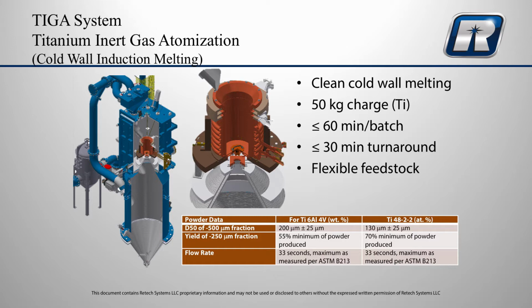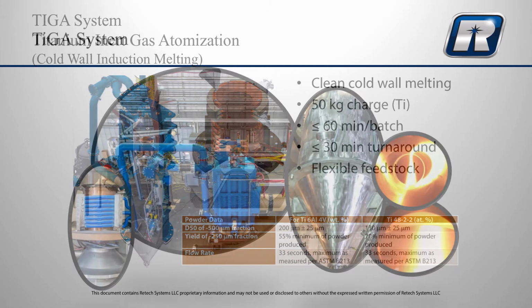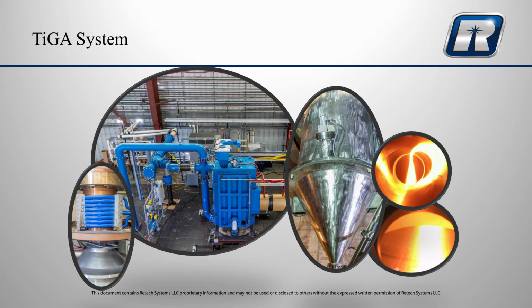There's a small feeding system in case some small alloy additions are desired to be made to the system. So that's what we call our TIGA system. It's cold wall induction melting bottom pouring. Just a few pictures here of the actual components, the tower and the melt chamber in the middle, the cold wall induction crucible over on the left, bottom pour, sitting on top of the tower inside the chamber, and actual atomization conditions shown over on the right.